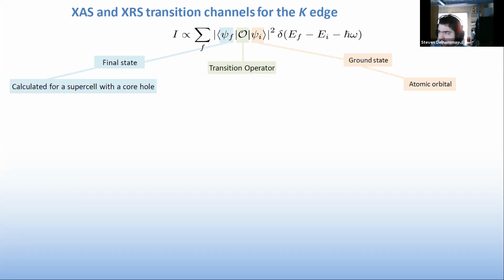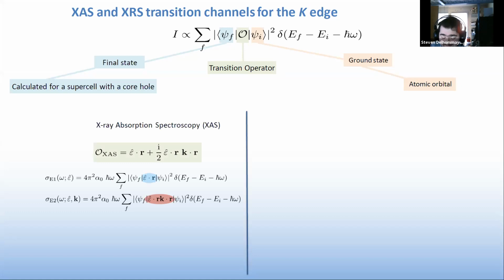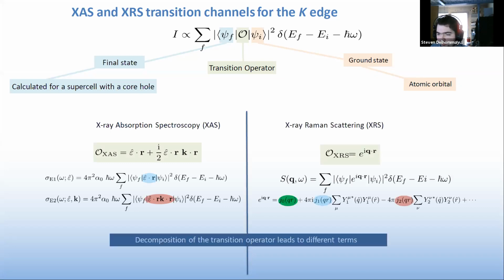So in this work, I mainly used two spectroscopy techniques. In fact, I used only two spectroscopy techniques. So first, the well-known X-ray absorption spectroscopy, where the core excitation is just caused by the absorption of an X-ray photon. And I also used X-ray Raman scattering, also known as non-resonant inelastic X-ray scattering. It's hard to say. So not to be mistaken with the RIXS that we saw yesterday in some talks. Here it's non-resonant, which means we use a higher energy.